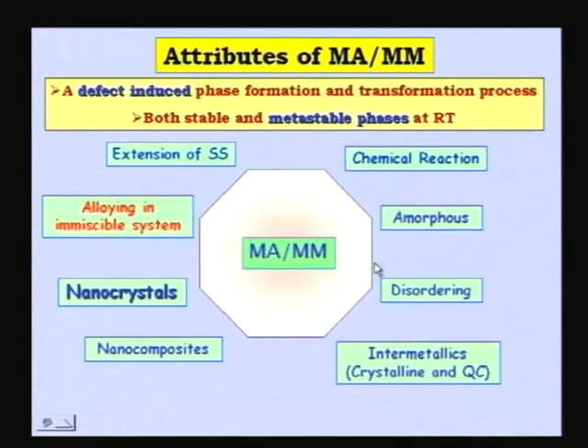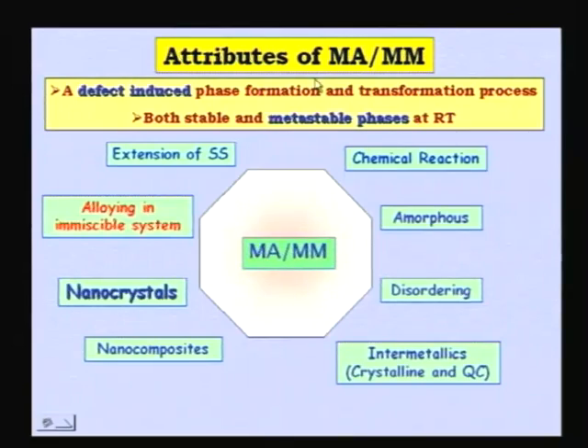And now, let us come to what you can achieve by this kind of mechanical alloying or milling process. If you look at the mechanical alloying or the milling process, basically it is a defect induced process. You are introducing a lot of defects into the system, breaking the powder particles into finer and finer particles, and during this fracture process you are introducing a lot of defects such as dislocations, vacancies, all kinds of defects are generated, and because of these defects that you are putting, the phase formation or phase transformations are enhanced, because the diffusivity is enhanced.